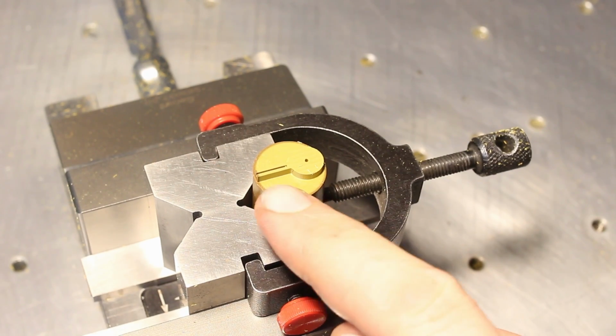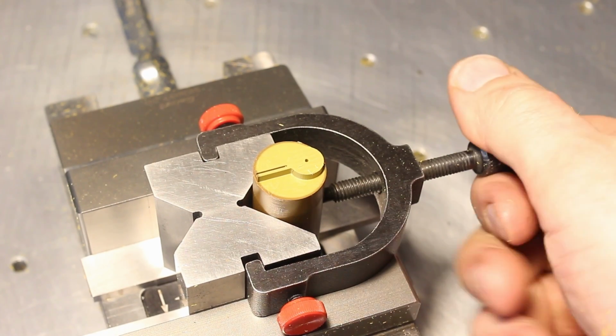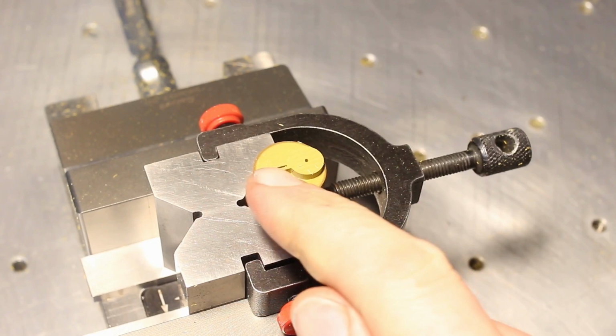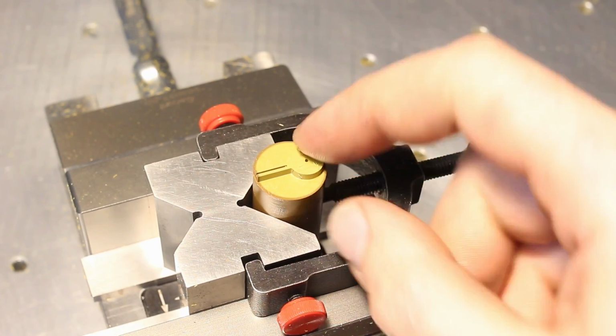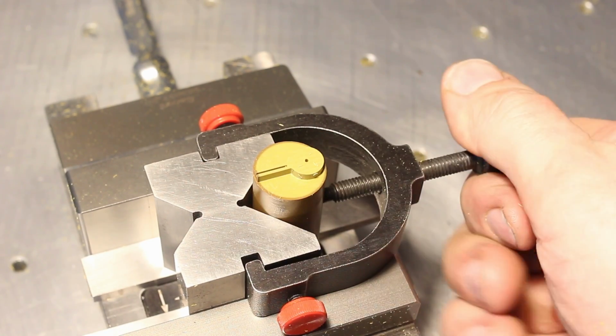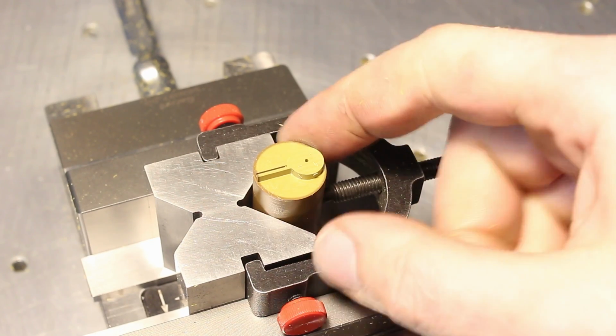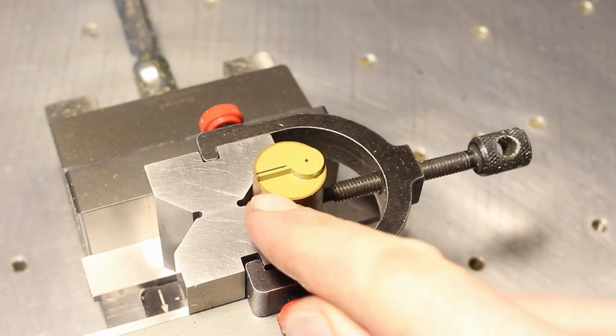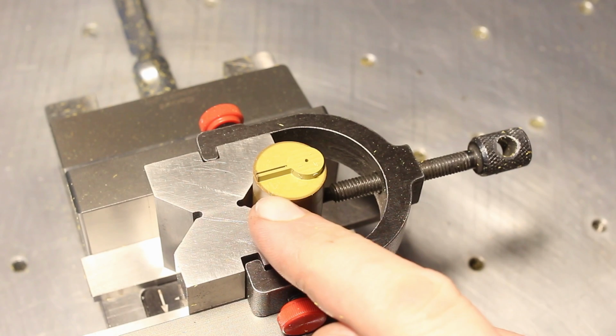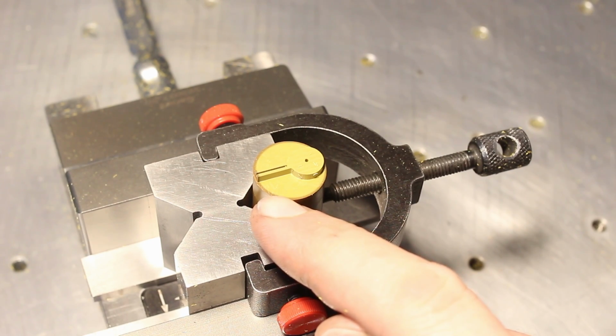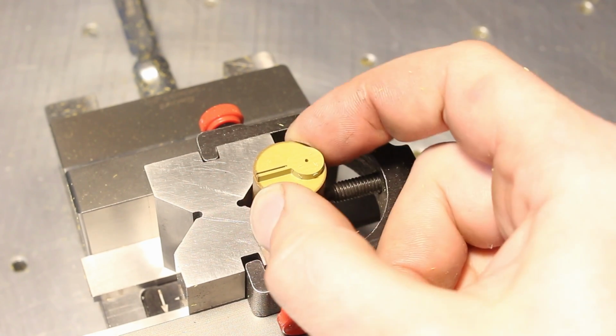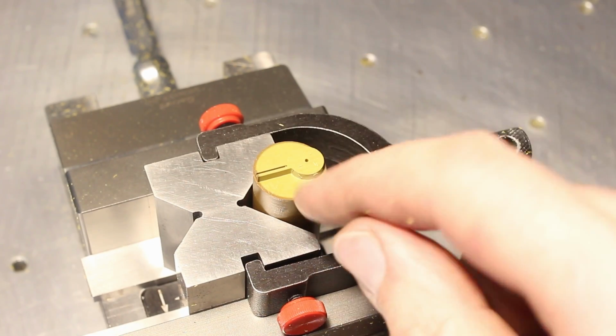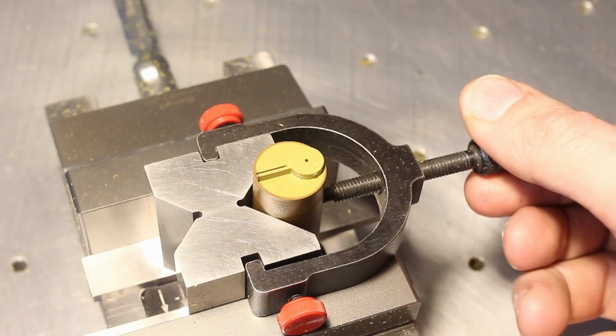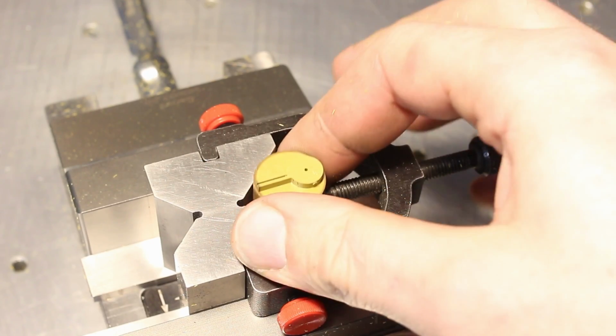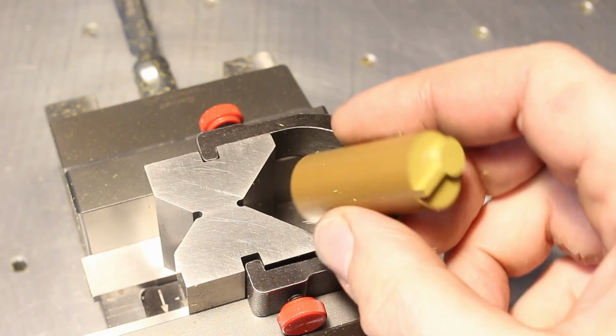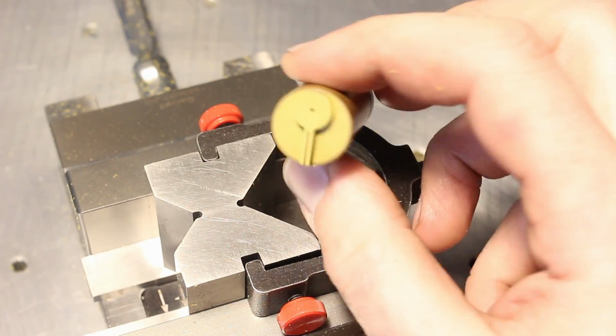We're over at the CNC mill and I just finished one of the contours of this part that I'm making. As you can see, the Torlon stock has almost like a tree bark. This is a 1 or 1.5 millimeter thick layer where the stock is a little bit harder than on the inside. That's probably due to the extrusion process or however this material is done.